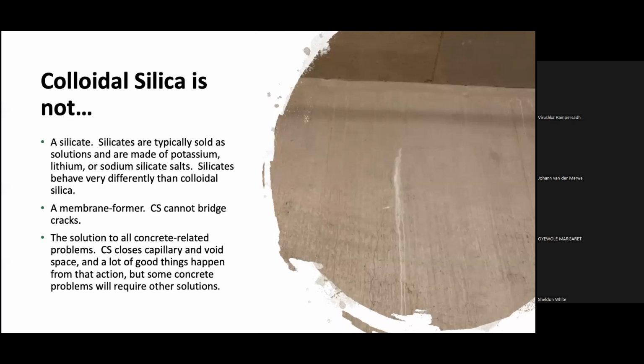It's important to remember that colloidal silica is not a silicate. You may have been thinking of some of the older technologies because silica and silicate sound so similar. Those crystalline technologies have been on the market since the 1950s in a lot of cases. Those silicates have a place in the market, and most of the time that's going to be in the floor hardener type area. However, colloidal silica is an amorphous silicon dioxide particle that's ready to react on the nanoscale. It's much, much more effective than the silicates. It's not a membrane former.